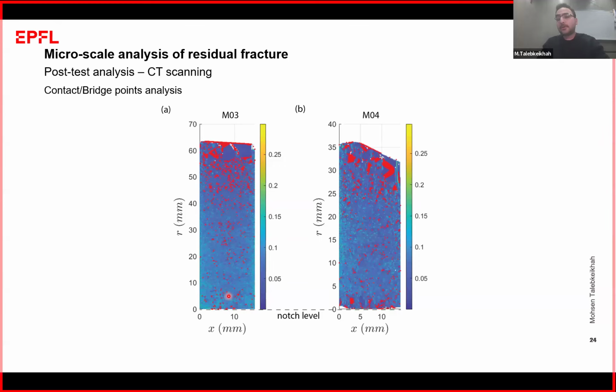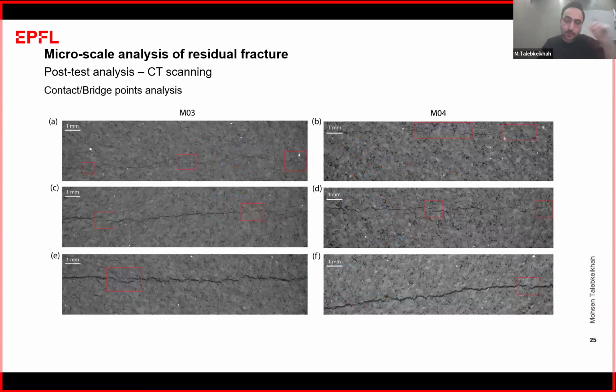To know what these red points exactly are, I brought the CT scan images at those specific red points that you can see here. For both experiments, the bottom row is close to the fracture inlet, the middle row is in the middle of the fracture, and the first row is close to the tip of the fracture.